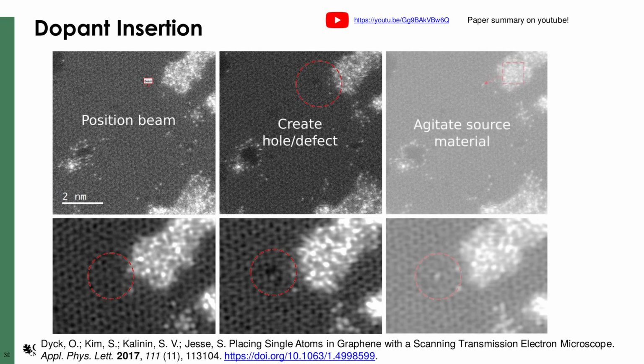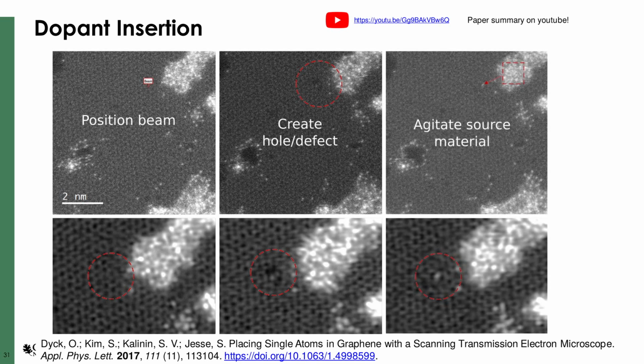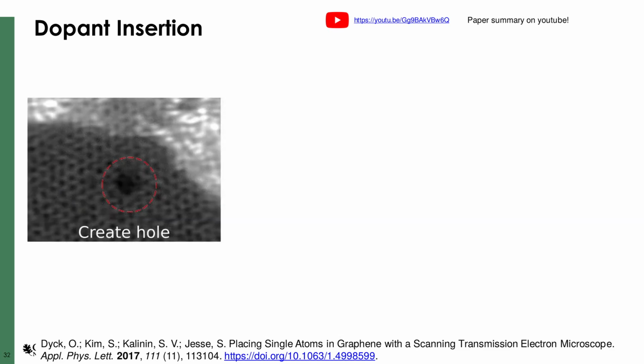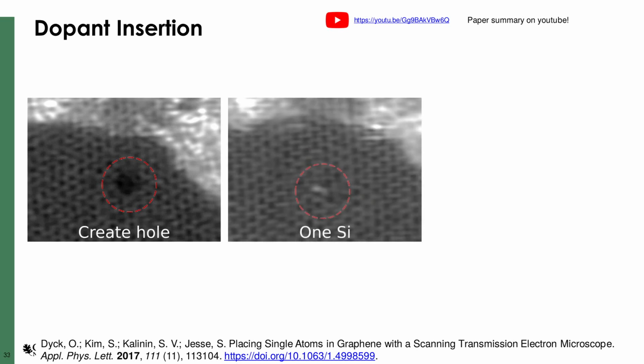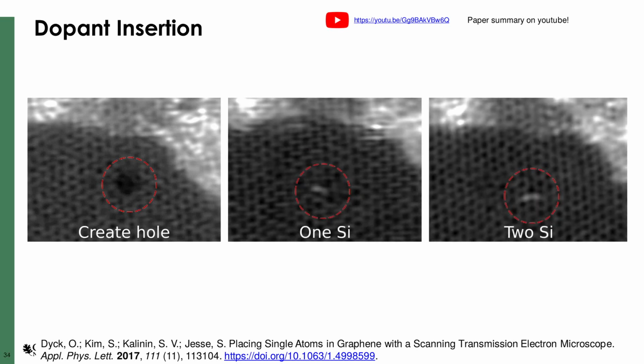The beam was then scanned over the contamination and a silicon atom was ejected from the contamination and attached to the graphene at the damaged location. Here's a second example. A small hole is formed, one silicon atom attached, and then a second silicon atom forming a dimer. This was very exciting. We are able to attach single silicon atoms to graphene.